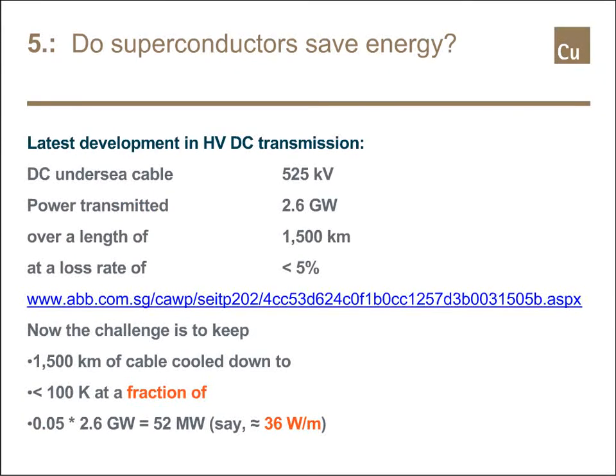The most recent application of conventional copper cable I came across is this message from ABB. They now released a DC undersea cable for 525 kV DC. So long, 400 kV was the maximum voltage for DC transmission. Now this cable transmits a power of 2.6 gigawatts over a distance of 1,500 kilometers at a loss rate of less than 5%.